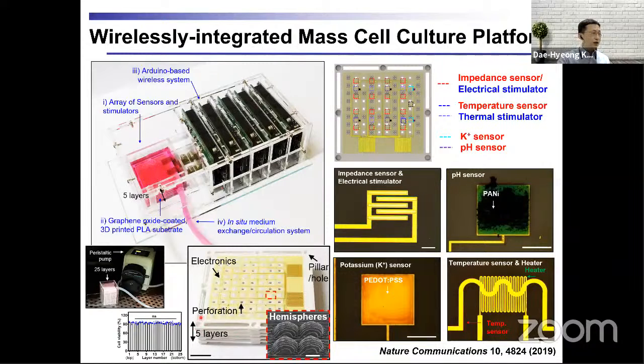We can also increase the number of layers up to 25 layers, as long as we use automatic media circulation. With this kind of media circulation, we can maintain cell viability over 90%, even with 25 layers. But in this case, we just use 5 layers, and each sensor and actuator array was connected to the Arduino board through an ACF cable. On each substrate, we have multiple impedance sensors, temperature sensors, potassium sensors, and pH sensors, as shown in these images. These sensing data can be collected wirelessly through the Arduino board, and all the data can be collected in the central server.